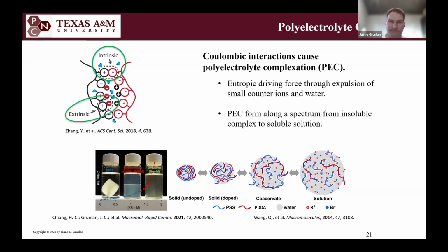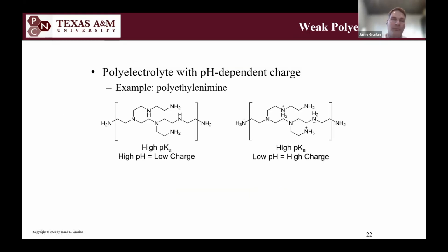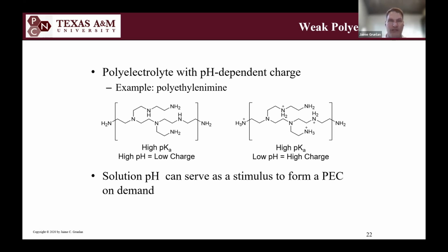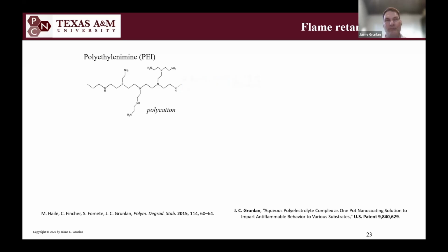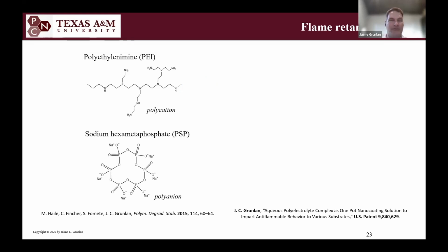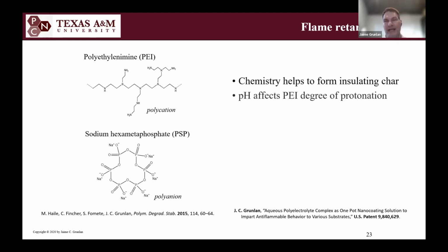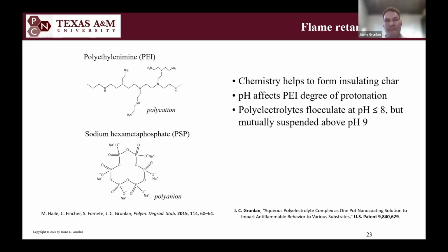And so let me see if I messed something up here. Okay, here it goes. Yeah. So if I use polyethylenimine as an example, you can see that at high pH, it has very effectively no charge. And then as I reduce the pH, more and more of the NH2 groups are going to become NH3+ groups. And so its charge density increases as I reduce pH. And so I can put polyethylenimine and something called sodium hexametaphosphate, or some people call it polysodium phosphate, PSP, into a solution together. And at pH 9, it's a pretty stable suspension, and it doesn't precipitate out of solution.